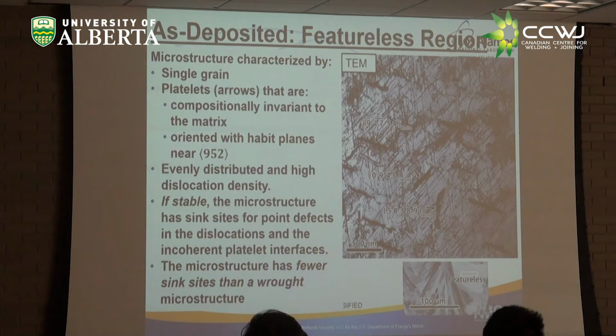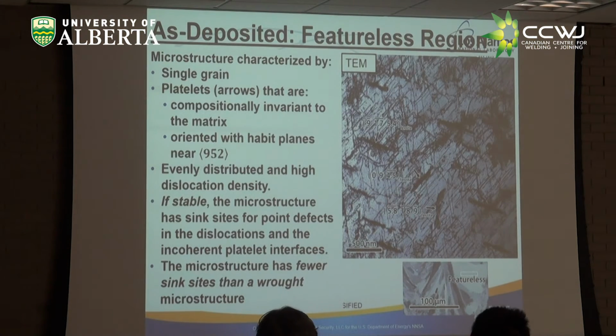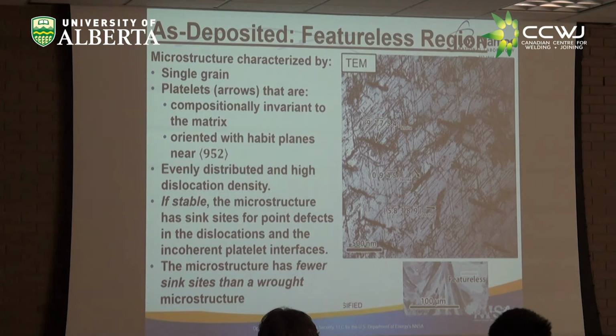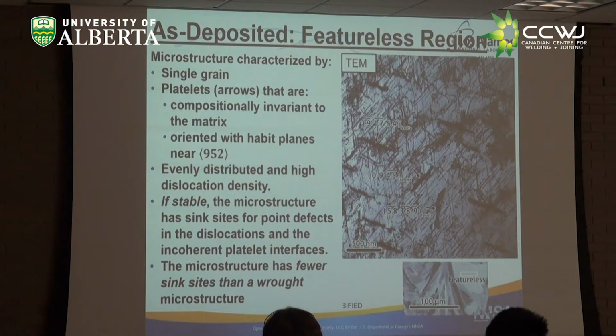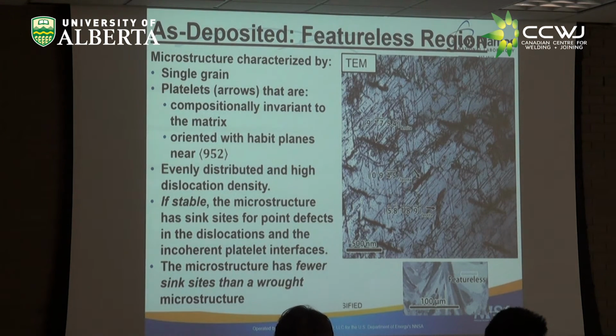So that's not quite right, but there's a very high density of dislocations all over the place. From a radiation tolerance point of view, if this microstructure is stable, and that's kind of a big if, there's many sink sites here for point defects. When you irradiate something, often in a reactor, when the neutrons hit it, you will form point defects, Frenkel defects. You'll knock an atom from the lattice into an interstitial site and leave a vacancy. That's called a Frenkel defect. And these defects cause hardening and radiation damage, which then change the properties of the material. So if you can find regions where you can remove those from the matrix, and if that interface between the matrix and those little needles is incoherent, it can actually suck up those defects and you will have less damage.